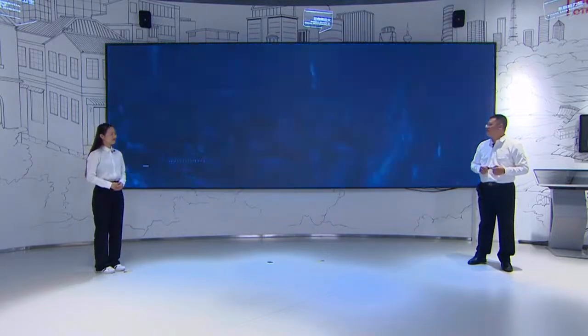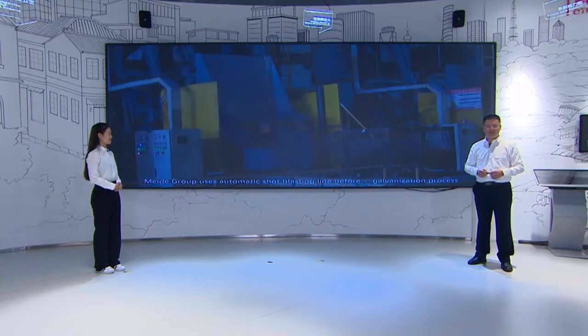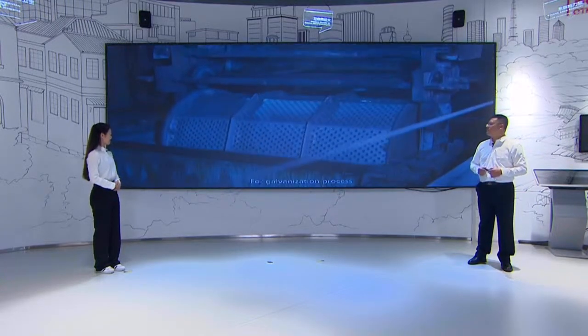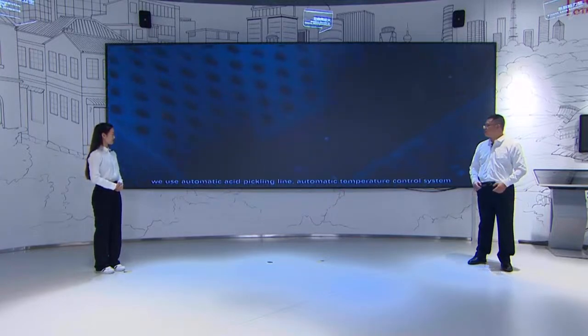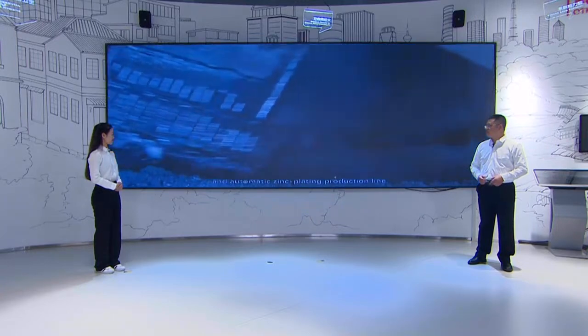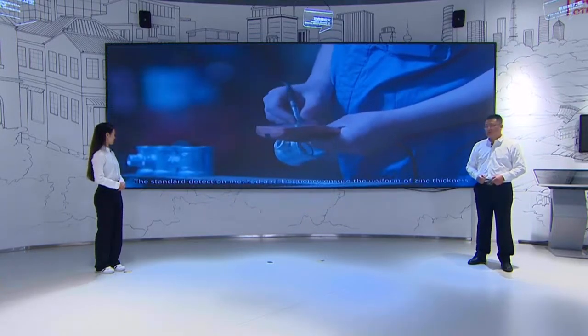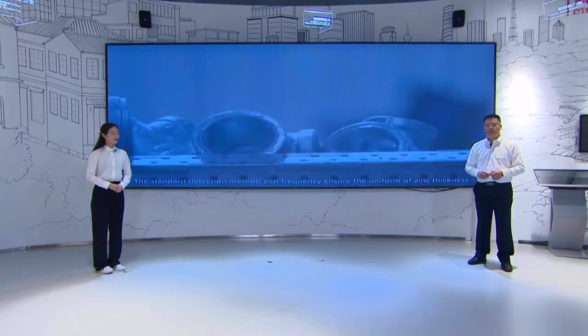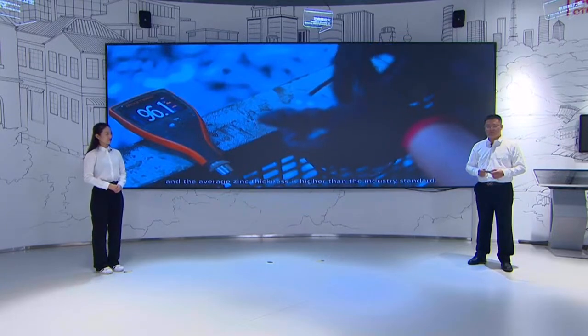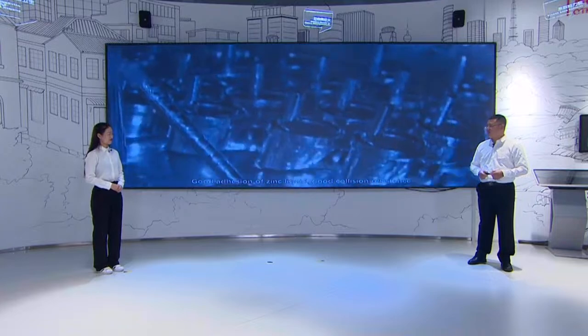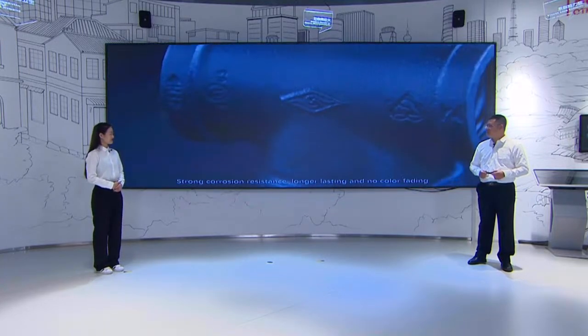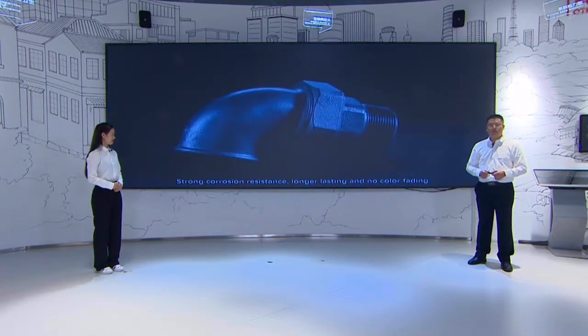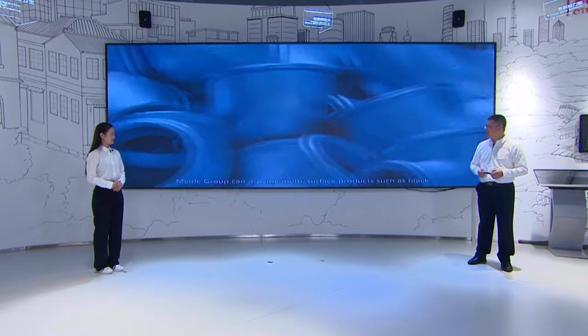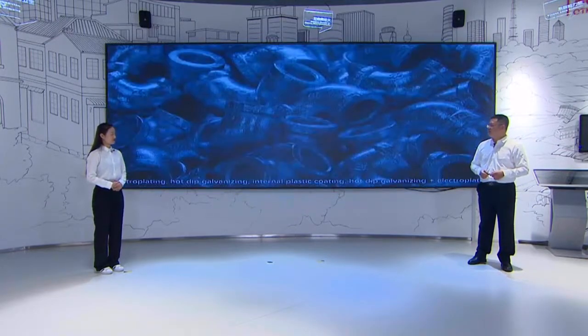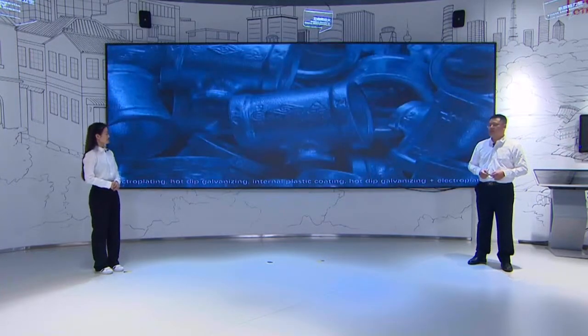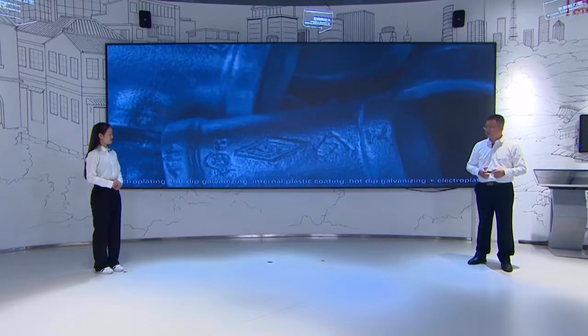7. Galvanization. Meide Group uses automatic shot blasting line before galvanization process. For galvanization process, we use automatic acid pickling line, automatic temperature control system, and automatic zinc plating production line. The standard detection method and frequency ensure the uniformity of zinc thickness, and the average zinc thickness is higher than the industry standard. Good adhesion of zinc liquid, good collision resistance, strong corrosion resistance, longer lasting, and no color fading. Meide Group can provide multi-surface products such as black, electroplating, hot-dip galvanizing, internal plastic coating, hot-dip galvanizing plus electroplating.